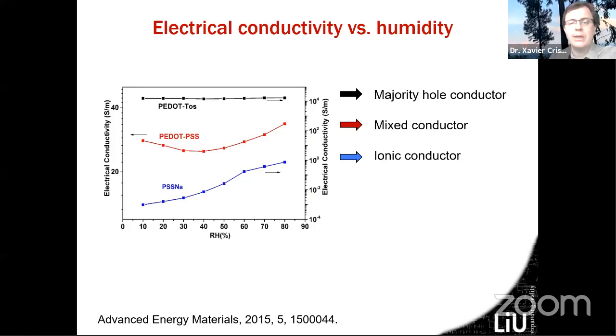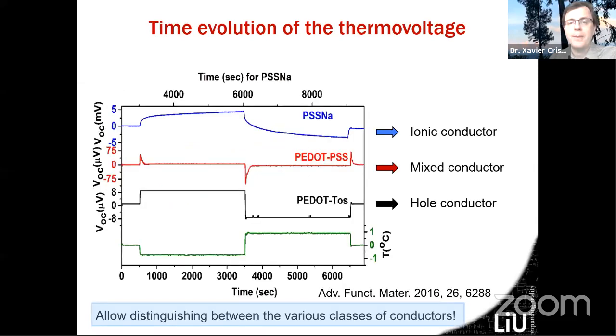But you see that there is also a response to humidity when the ionic carriers kick in. This is even more visible when you look at the evolution of the thermovoltage, that is to say, the Seebeck voltage. So in these experiments here, in the bottom, you see this is what you apply as temperature gradient to the material. You see a small temperature gradient here.